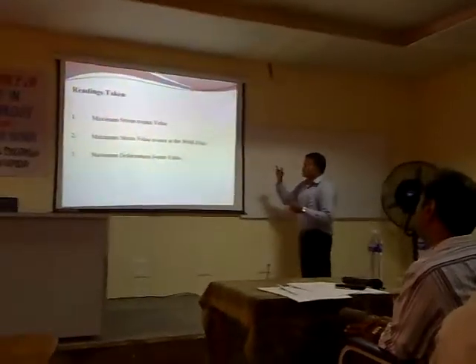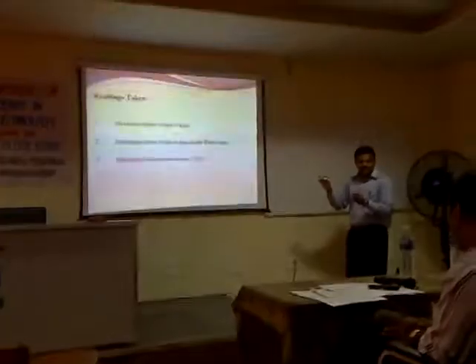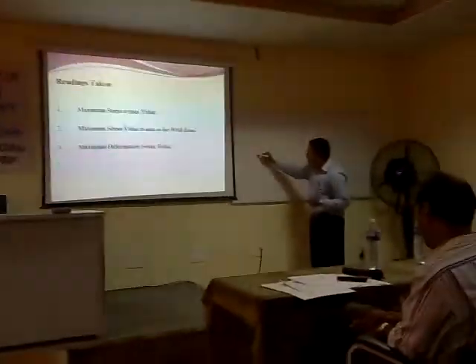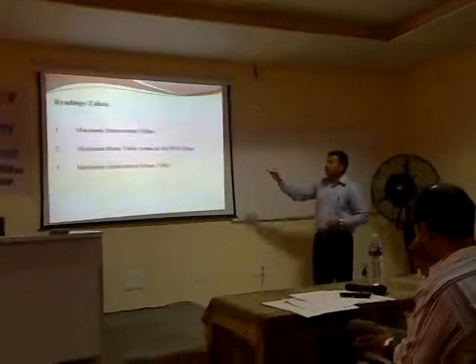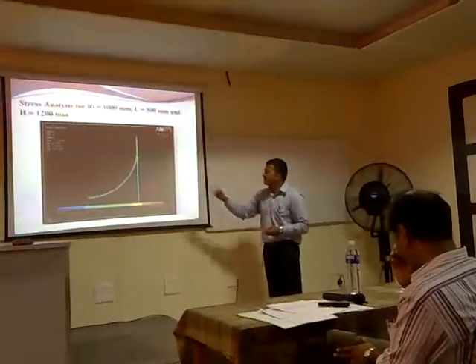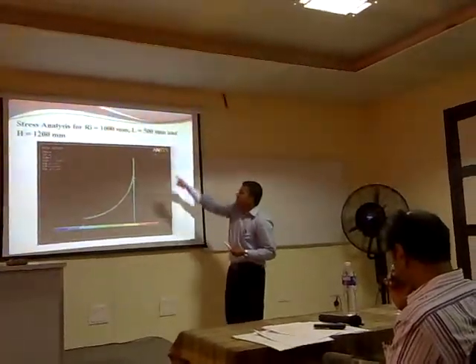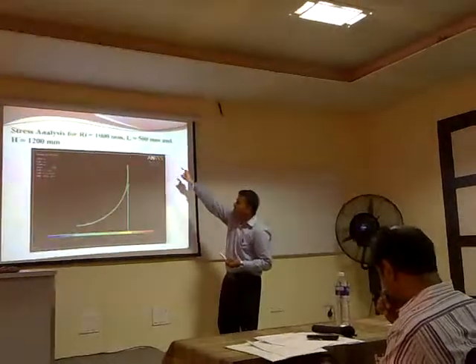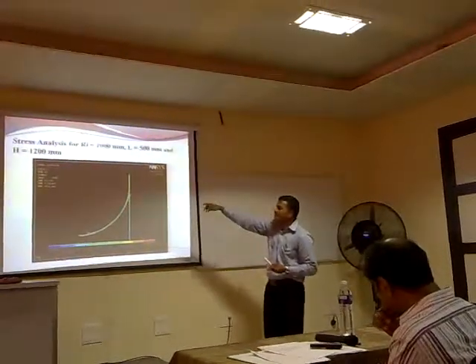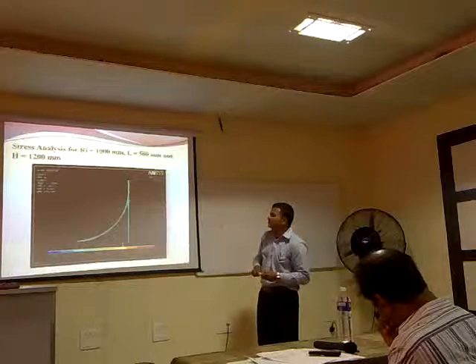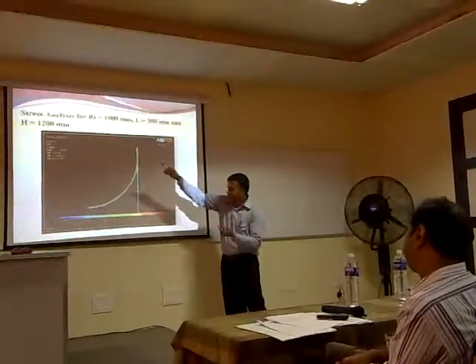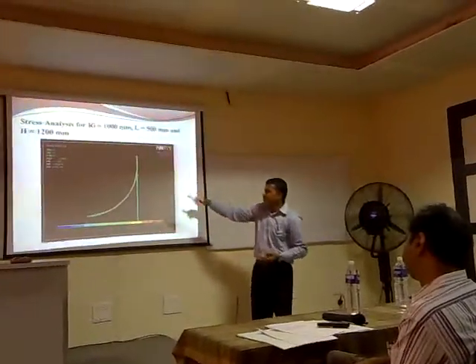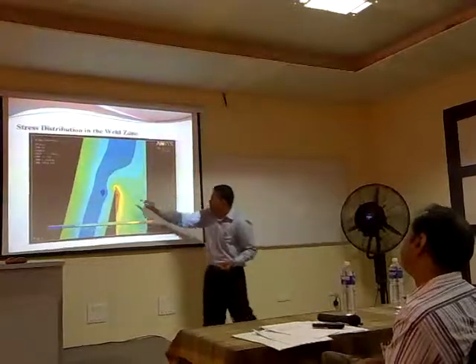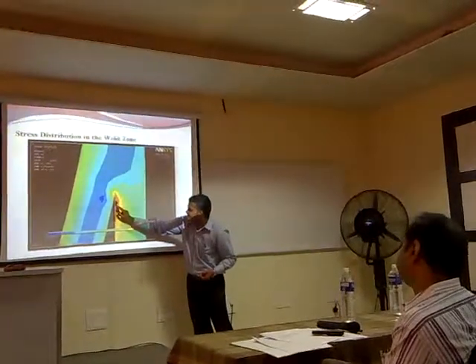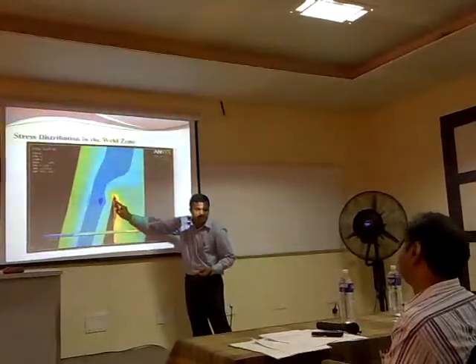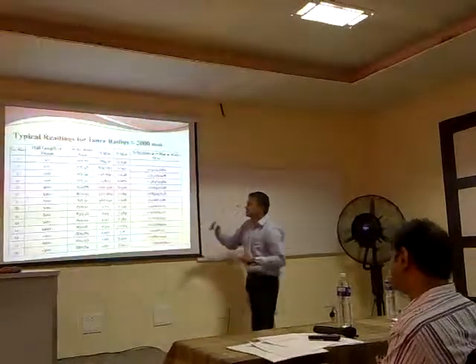Readings taken are the maximum stress value in the whole geometry, the stress value at this particular point, which is the area of concern, and the maximum deformation in the whole geometry. Now for a typical analysis, where the inner radius is 1000 mm, length is 500 mm, and height of skirt support is 1200 mm, I am getting these values of maximum stress and maximum deformation. For that particular zone, I am getting maximum stress over here, and this is the weld region of my interest.